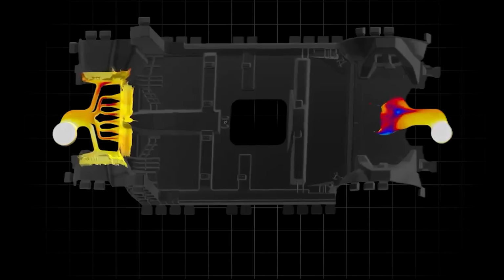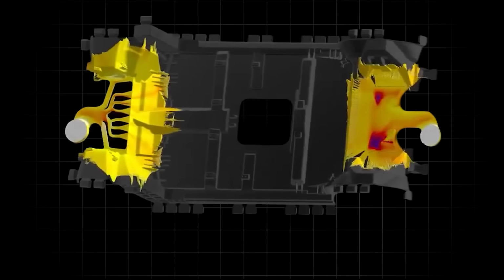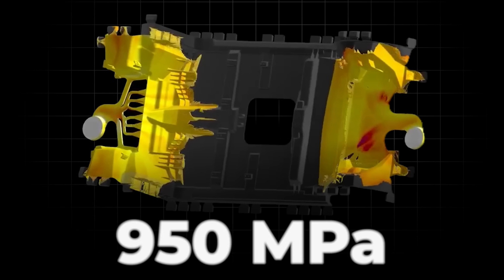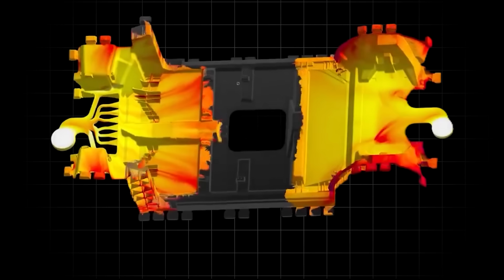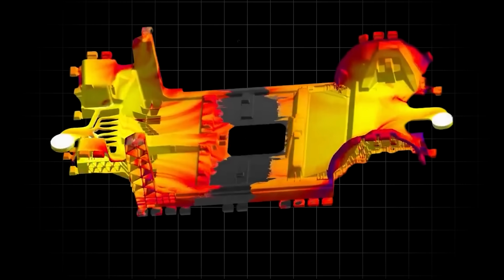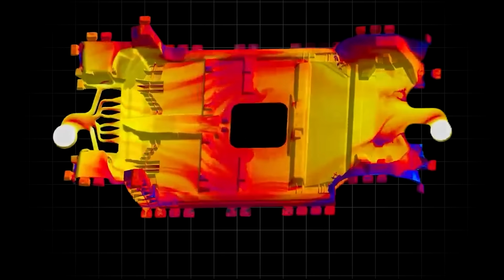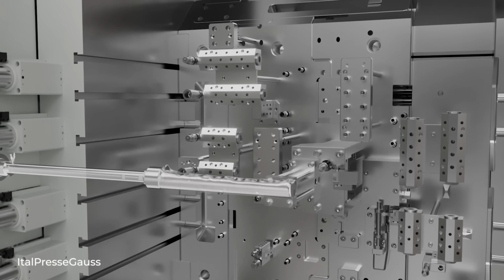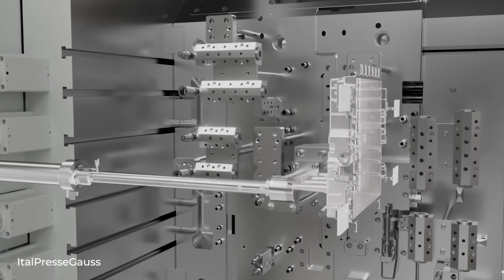Tesla-based engineers are targeting a material capable of maintaining approximately 950 MPa of yield strength at temperatures reaching 450 degrees Celsius while resisting the thermal fatigue that normally destroys conventional casting tools. For the die casting industry, this addresses one of the biggest manufacturing bottlenecks.